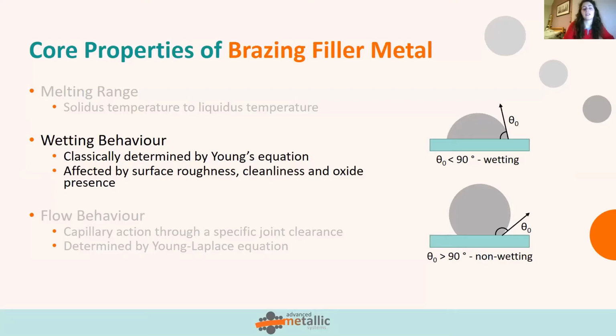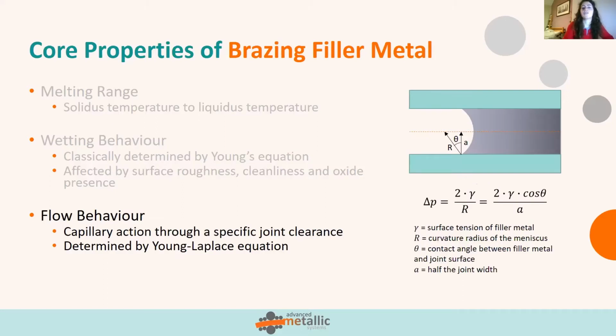Other factors that affect the wetting behavior are also things like surface roughness, cleanliness, and oxide presence. And the last of the core properties is the flow behavior. Filler metals move through a joint through capillary action, so the flow behavior is really important, and this is influenced by the melting range. It also means that you can tailor a joint clearance based on the flow properties, or you can base which alloy you select on the clearance that you need. So a better flowing alloy would be better suited to a smaller clearance gap.